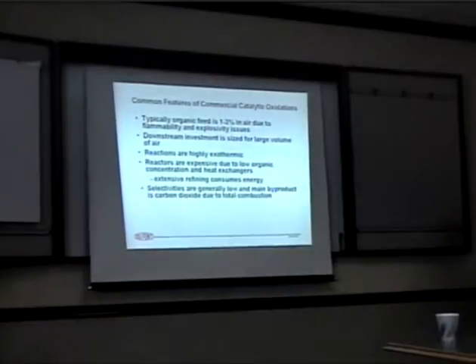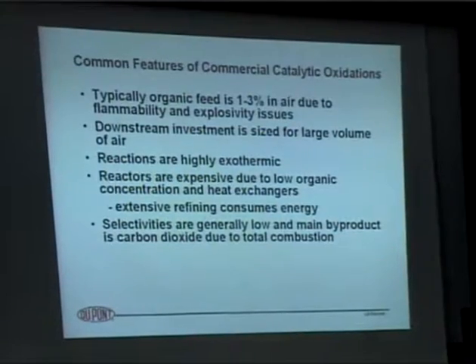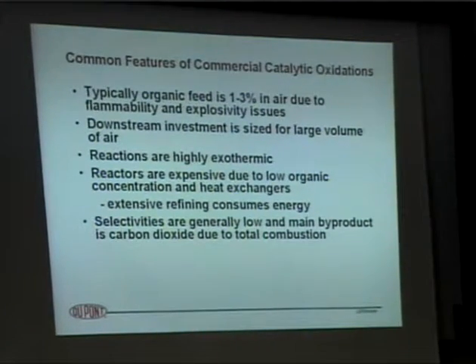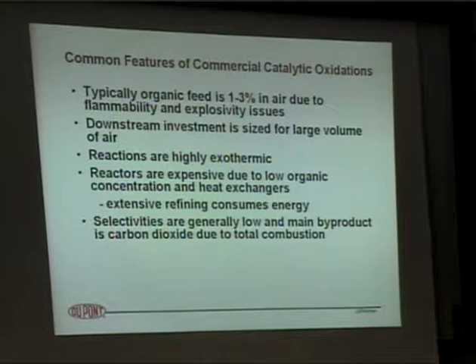And the reason for that is because organics and air form flammable mixtures. So in order to prevent the reactors from blowing up, you have to stay below the flammable limits. And that oftentimes means you're operating at 1 or 2% hydrocarbon in a stream. So here you've got one of these big reactors I just showed you. You're passing 1% hydrocarbon and 99% air through that reactor. And all of the equipment downstream, the distillation columns and everything, has to be sized to handle all of that air that's in there, when you really only want to deal with a small amount of organics. So that's why it's a high investment process, because of the flammability issues. So you see the investment is sized because of all that air.